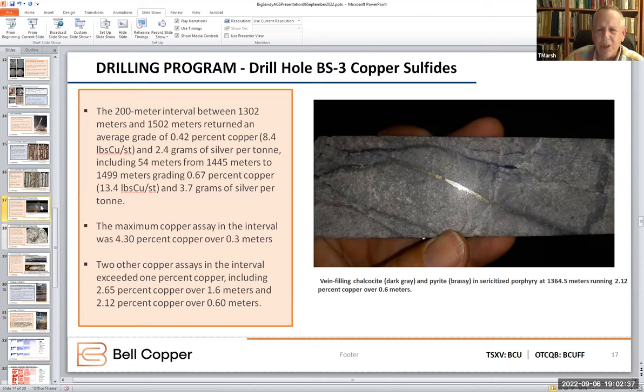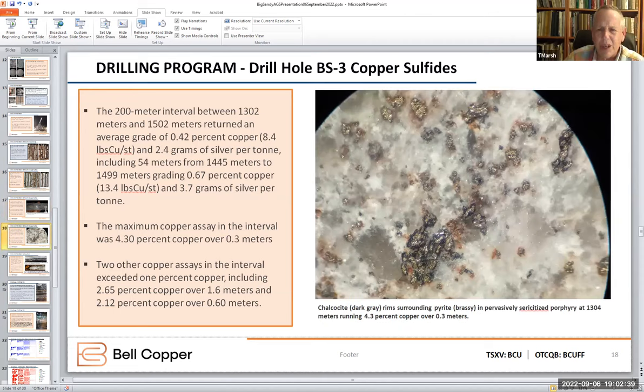Down to slide 18. This is a pretty typical picture of the texture, photomicrograph, field of view about 7 millimeters. The grains of pyrite are roughly a millimeter across, but they've got a dark gray, silver gray rim of chalcocite surrounding the pyrite. It's just a good old supergene enriched chalcocite. You can see the texture of the porphyry is pretty much obliterated. You can make out a few quartz eyes. Most of the rest of the porphyry is just muscovite.